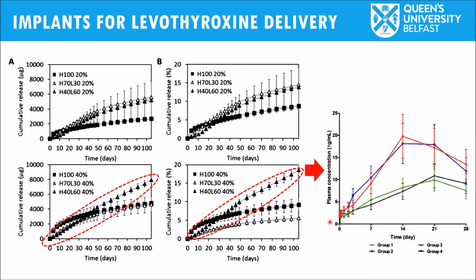So we observed that in the formulation that contains a mixture of high molecular weight and low molecular weight polycaprolactone, we have a higher area under the curve and a more efficient delivery of the drug, while in the formulation containing only high molecular weight polycaprolactone, we have lower levels of the drug in plasma. Obviously, this test was done with half an implant. We cut the implant in two, and rats were implanted with half an implant. Obviously, this is just a preclinical study to see if the implants were capable of sustaining the delivery. In this test we achieved at least 28 days of release of the drug.